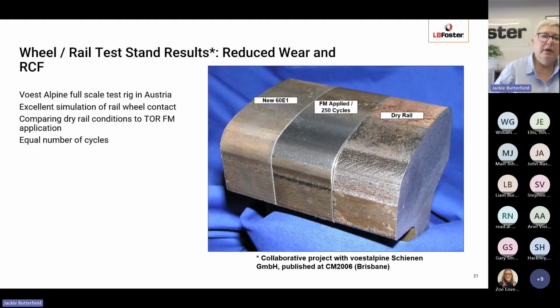So the second one is a top of rail example on rolling contact fatigue. This is a laboratory test that was carried out in Austria in the Voestalpine full-scale test rig. This was used to simulate the rail wheel contact, comparing dry rail conditions with a top of rail application, in this case Keltrac, with a dry wear situation. The pictures show on the left-hand side a brand new rail profile. The center is a section of rail which has gone through the full-scale rig, and top of rail material has been applied.